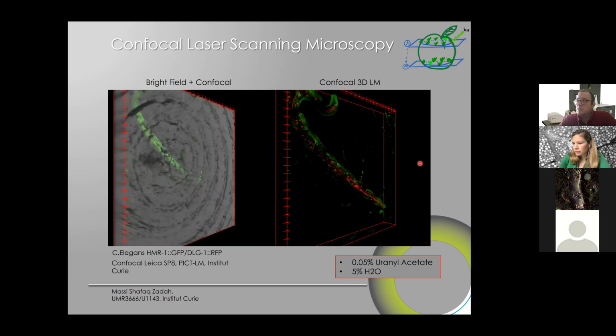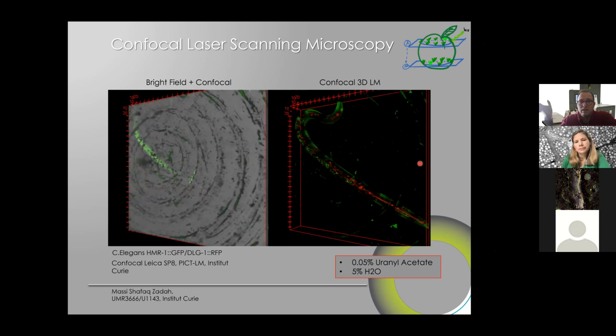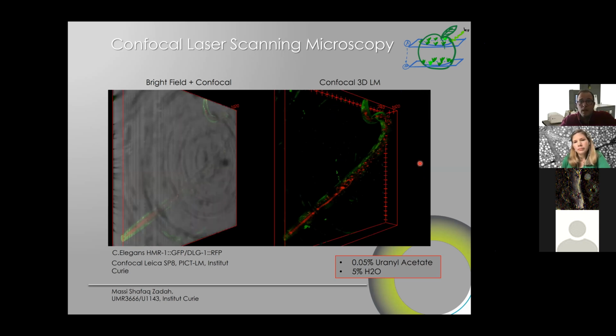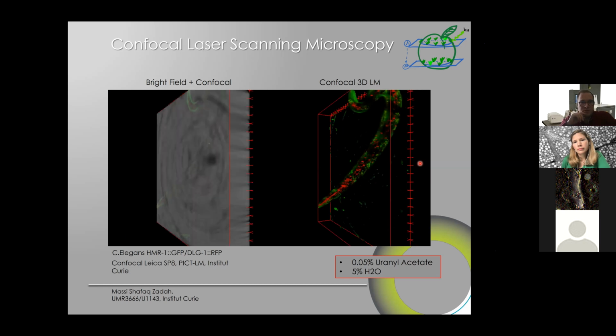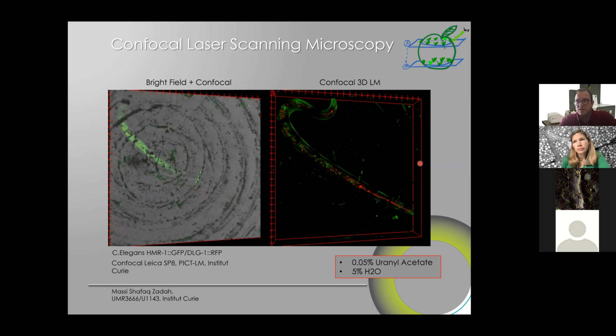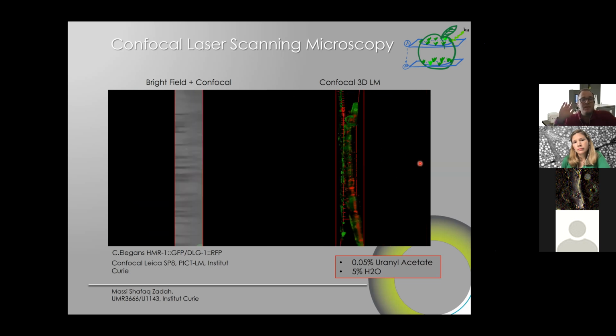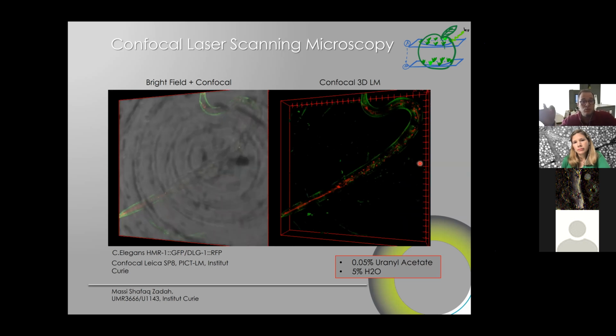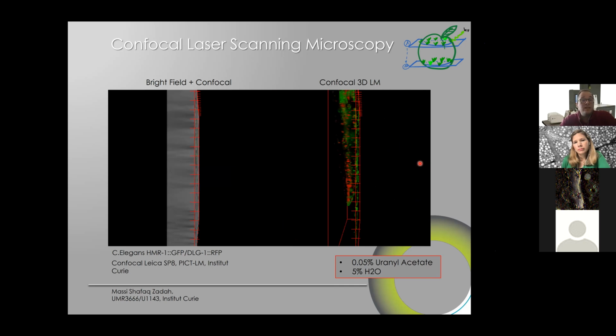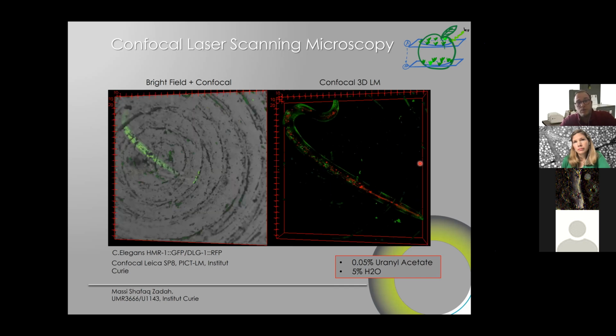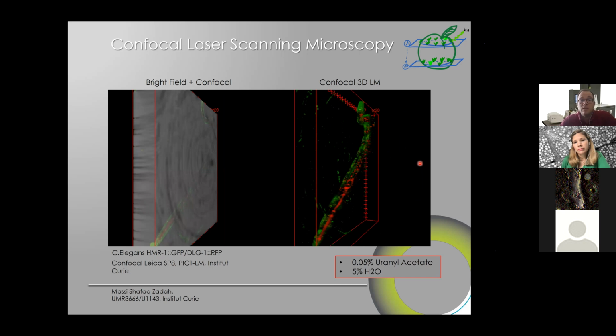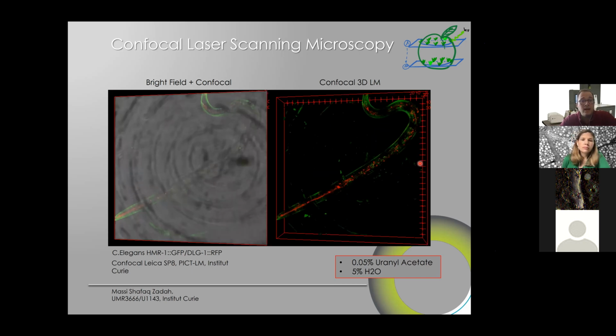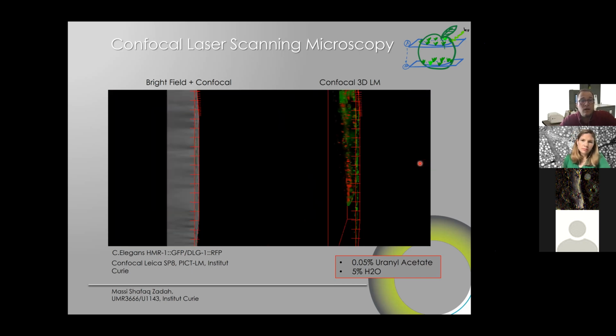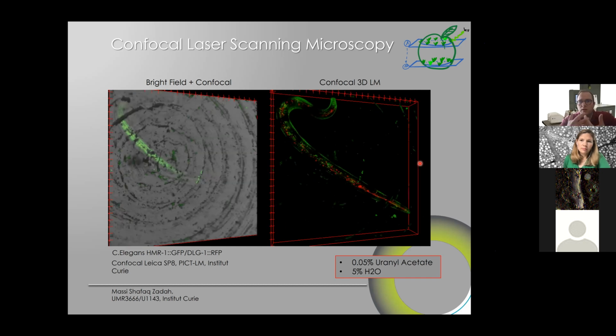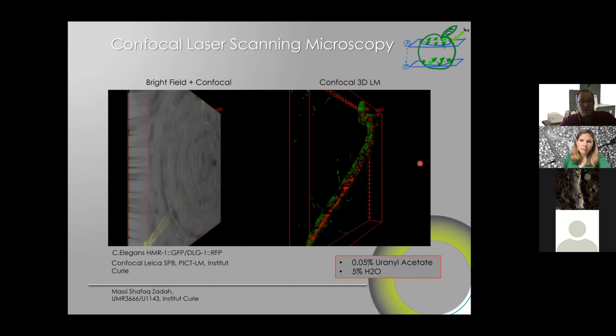Not only did it give very nice results, but we did not observe any bleaching, and it did not alter the structures underneath afterwards. So this block was imaged at the Curie Institute, and then I sent it to Chris so that he could do the volume electron microscopy. And so that he could get familiar with the block, he went back to an epifluorescence microscope, and he could image the same worm and look at it again. And he was not looking for the fluorescence. It was not bleached, and we were using, again, a huge amount of laser power.